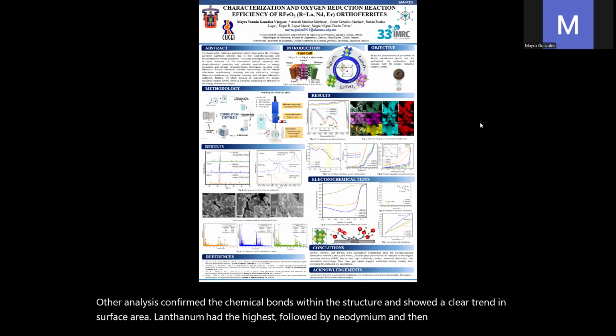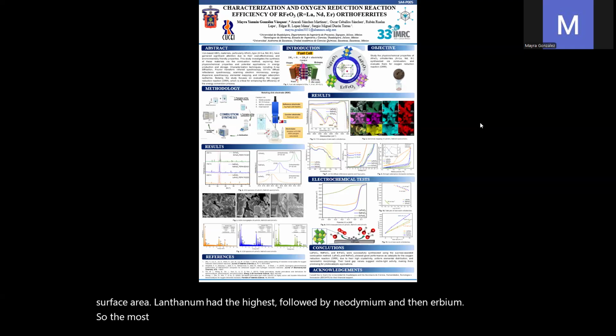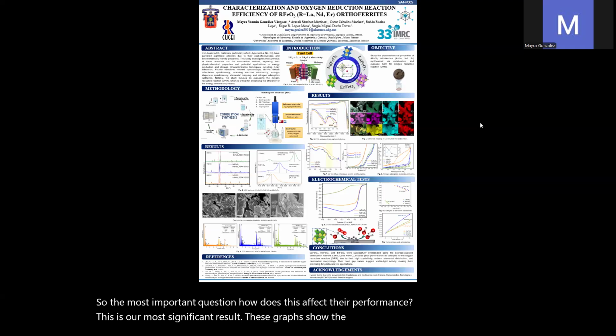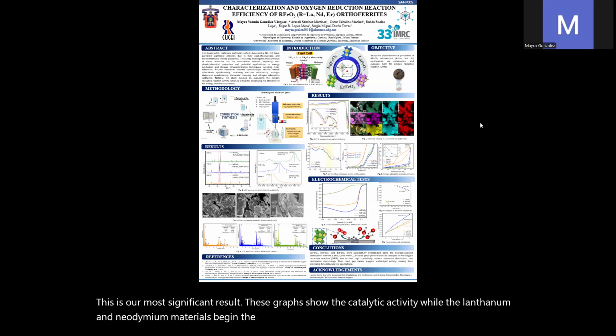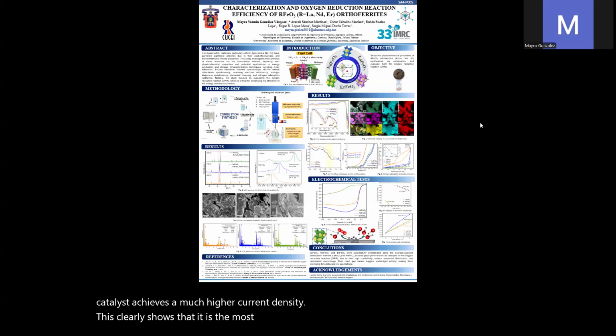So, the most important question: how does this affect their performance? This is our most significant result. These graphs show the catalytic activity. While the lanthanum and neodymium materials begin the reaction at a similar potential, the neodymium-based catalyst achieves a much higher current density. This clearly shows that it is the most active catalyst of the three. In contrast, the erbium material shows very little activity.